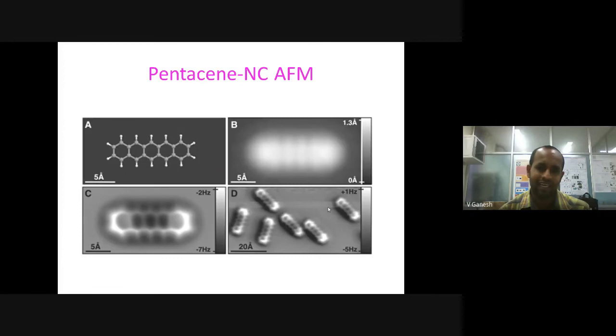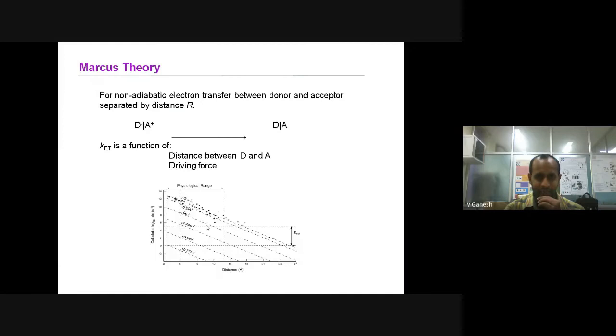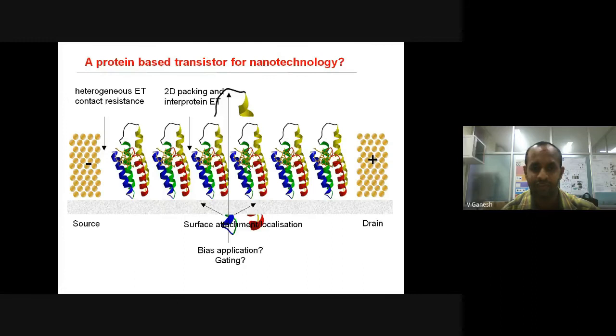The one I showed, naphthalene thiol, is just two benzene rings. If we keep on adding like this, this is called the pentacene, where we have five benzene rings, and you can see such molecules arranged on the sample substrate very, very beautifully. You can look at the pi electron density distribution using such AFM images. Okay, like this. I can keep on showing a lot of images, depending upon the molecule. And this is the theory I mentioned just a while ago. This is called the Marcus theory. He proposed a theory with respect to change in distance, how the electron transfer rate constant varies. Okay. So that theory was validated between donor acceptor molecules using such scanning probe technique.